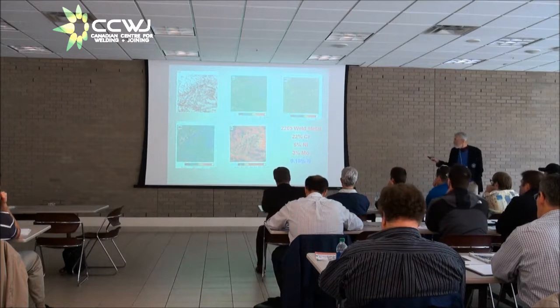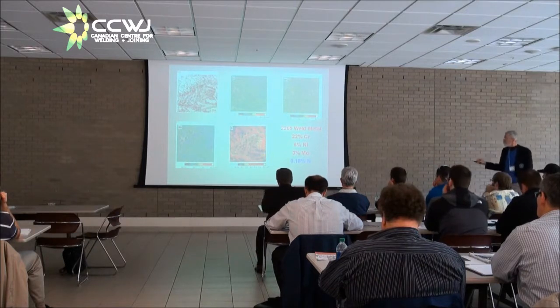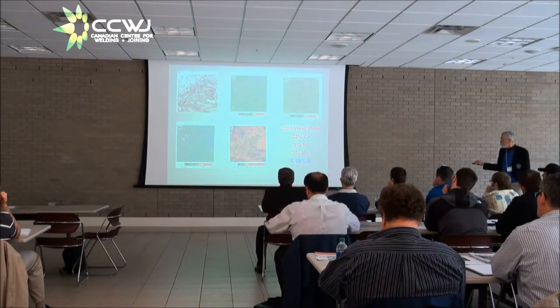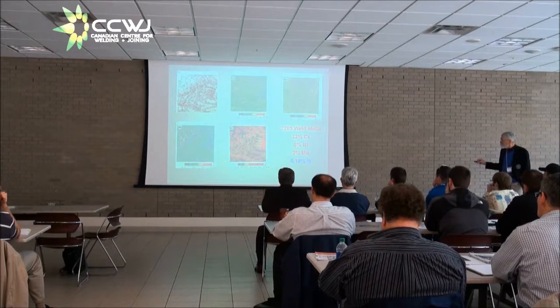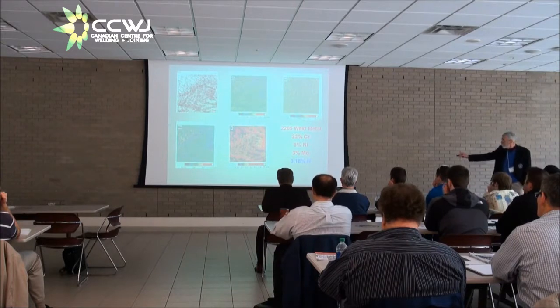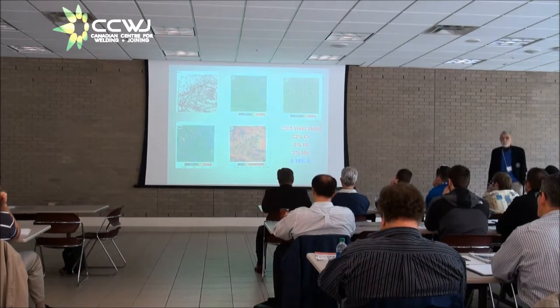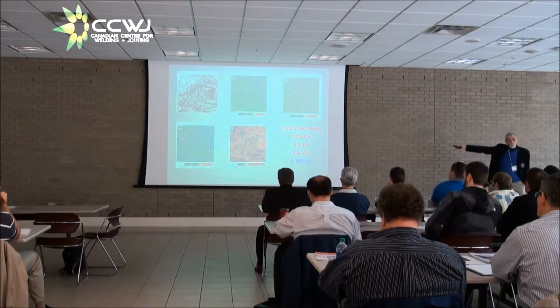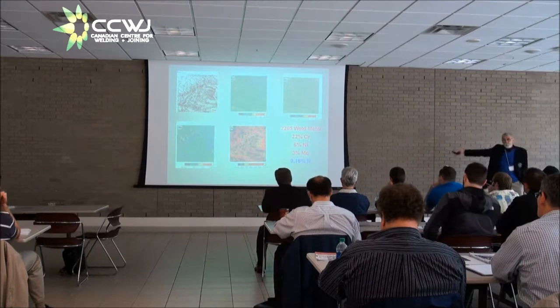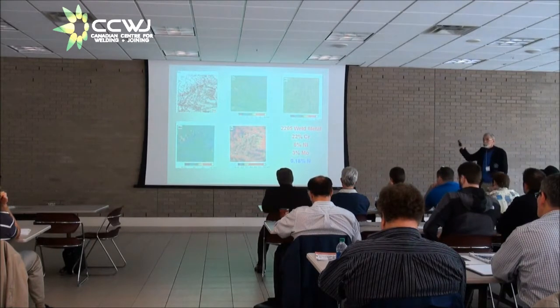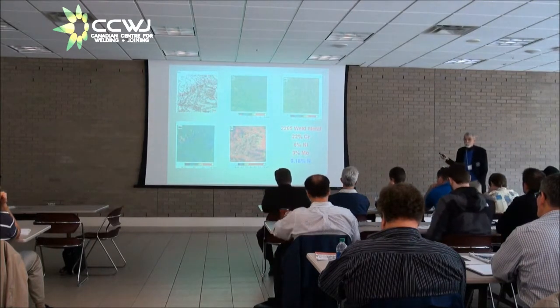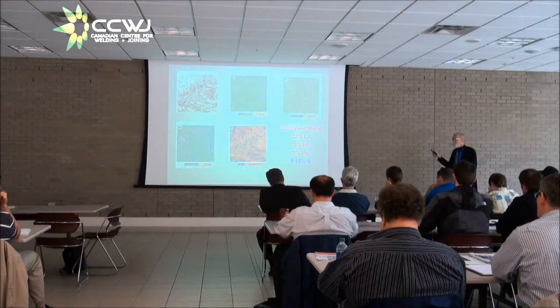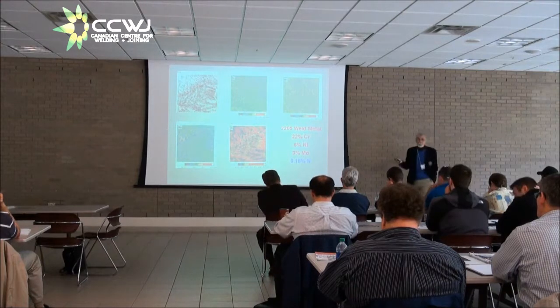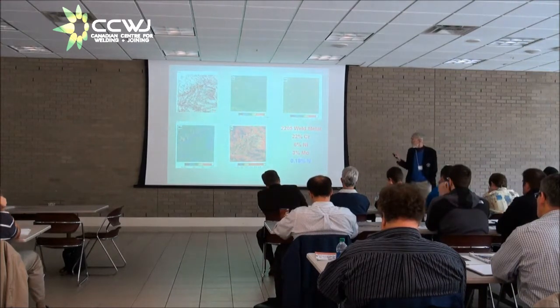And if you look at the nitrogen map, you can see the same big ferrite grain outlined by high nitrogen on the grain boundary. You've got all of these austenite plates inside the grain, which are also full of nitrogen. And then you've got ferrite areas that are completely clear of nitrogen. Now you've got good properties. It's the nitrogen that makes the alloy weldable, because that promotes formation of austenite at high temperatures, so the diffusion can go on.